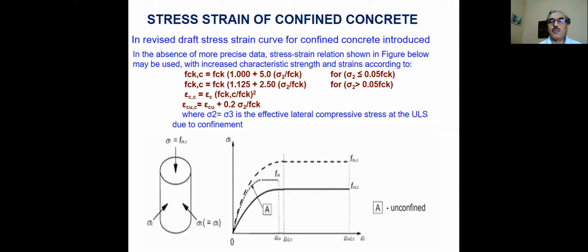Coming to the stress strain curve of confined concrete - we didn't have much data on this. For the previous curves of different grades, we had a lot of research done in our country at NCB and at IIT, based on which we agreed to those values. But for confined concrete, we are taking these values mainly from the Eurocode, where the strength, depending upon the confinement, along with the strain and stress values, are modified as per the equations given.